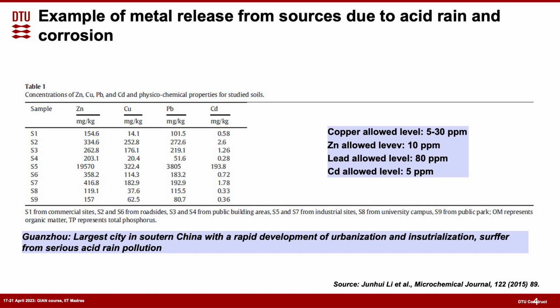We'll look at that in detail, but before that, you can see here that the allowed copper level is approximately, and it's a little bit difficult because it depends on which standard you look at, but at least we can take it as approximately 30 ppm per kg of soil. Allowed zinc level is around 10 ppm, lead is around 80 ppm, and cadmium is around 5 ppm. So these are the kinds of levels which you can allow in the earth, but you can see that the amount of metal released here is significantly higher than that. If you look at zinc, copper, many places it is more than that, or lead or cadmium, it is much higher than that.